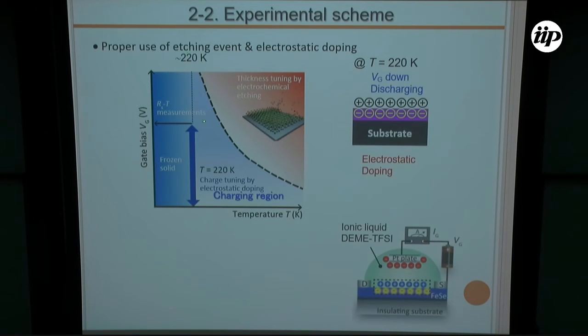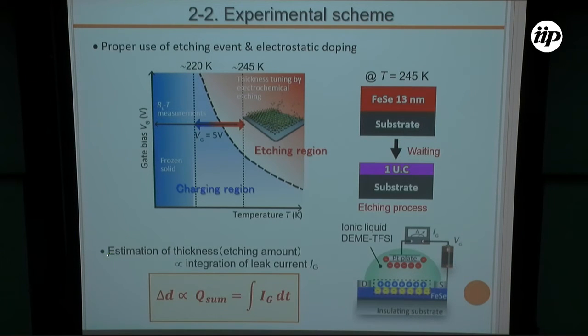On the other hand, at around 220 Kelvin, this etching completely stopped, and only electrostatic charging is possible. And the most important parameter in this work is the thickness. The thickness is estimated by assuming that the decrease of the thickness is proportional to the charge amount, which is derived by the temporal integral of the leak current, Ig. After many experiments, we checked that this relation is very reproducible, so the thickness parameter in the following data is reliable. Okay, let's go to the data.